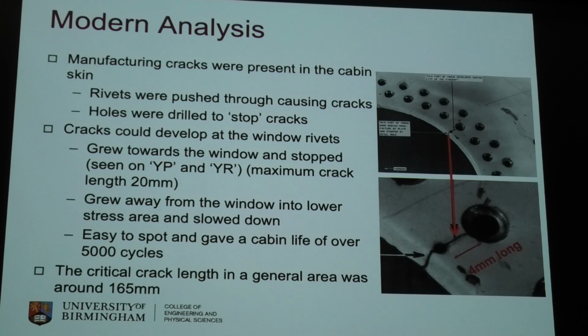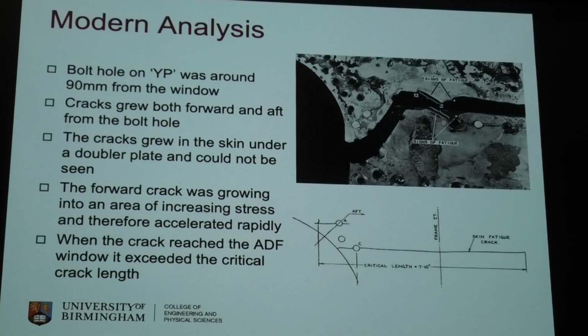So Yoke Peter, that did that inaugural flight to Joburg, was likely to be the one that caught up because it had been in service the longest. And we know that the crack grew under a doubler plate, so even if they looked at it on that flight, it was under a doubler plate in the skin. So even though it was probably getting on for about 6 inches long, the chance of actually finding it was slim. And there's a story about a 737, looking at a crack that long and going, I thought the flight crew knew what they were doing. Different accident, but an interesting story.